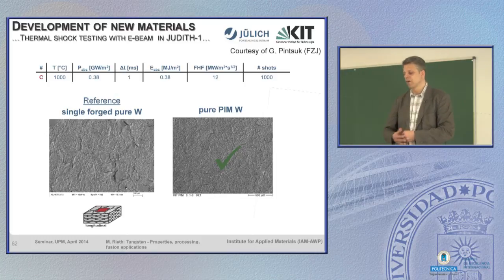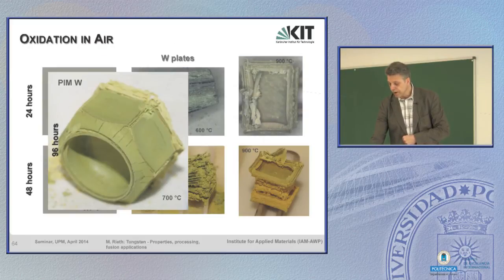Thermal shock load, or a thermal high heat flux test, that's not shock loading. This has been done in a facility in Garching, you see it here. It's inside the vacuum chamber, and this is loaded by intense hydrogen, and sometimes a mix of hydrogen and helium particles. And well, you see it on the color, it's very bright, so the surface temperatures, I think in that case, are around 1500 C or so. It's tested also with pulses or not, you can do it as you want. And after the test, you can see how the material behaves.